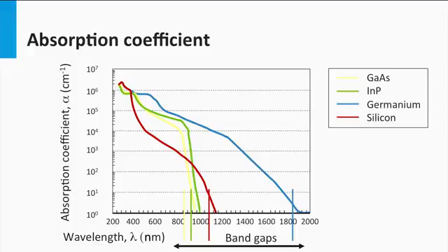Materials with an indirect bandgap, like silicon and germanium, have smaller absorption coefficients. Only in the very blue part, below 400 nanometers, silicon has a direct bandgap transition. Silicon is a relatively poor absorber and therefore thicker absorber layers are required in reference to gallium arsenide to absorb the same fraction of light.